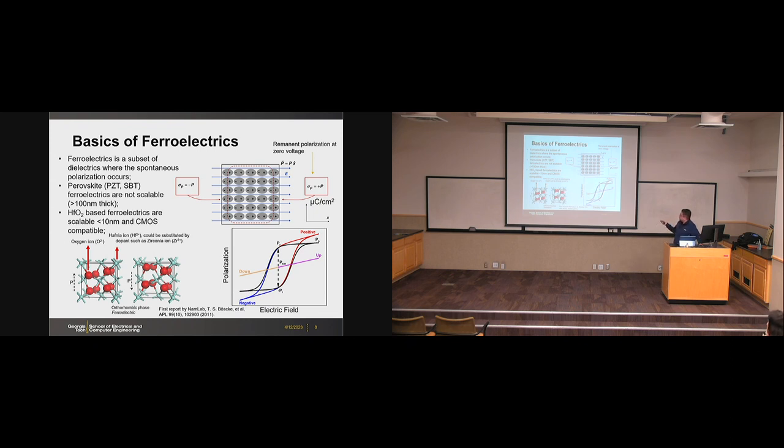And then essentially it is a surface charge density, with units like microcoulomb per centimeter squared, used to characterize the surface charge density. So this could be regarded as a memory state, because you can have this so-called polarization versus electric field hysteresis. So here when you apply a positive voltage, you can polarize up all the dipoles, and then you get some surface charges, maybe positive on one side. And then when you reverse the voltage of the electric field, you can polarize the state into another direction. Then you have negative charge on the surface. So here, depending on the surface charge density, you can have two memory states, and this is called the remnant polarization.